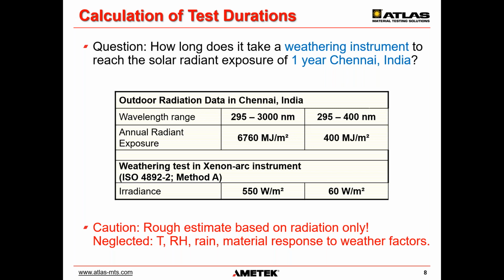Here's an example. How long should I test in a weatherometer to simulate 1 year of exposure at the ATLAS test site in Chennai, India? Well, we know how much radiant energy we receive at this location, and I put that here. It is 400 megajoule per square meter per year on average. Now let's say that we are running a laboratory test in a xenon arc instrument following method A of ISO 4892 part 2. And this is 60 watt per square meter using an outdoor daylight filter set without dark phase. Rain is included, but no dark phase. So we have 60 watt per square meter in the instrument and 400 megajoule per square meter to achieve. How long does it take?